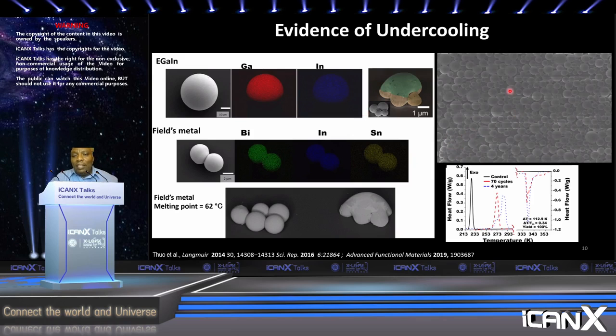So this was the video where we mill the particles and you can see them popping and flowing and they coalesce. But also we can confirm by DSC where we see that the metal with a melting point of 62 can be undercooled all the way below minus 40 degrees centigrade. So from 62 all the way to minus 40, and even sometimes you can get to minus 50.